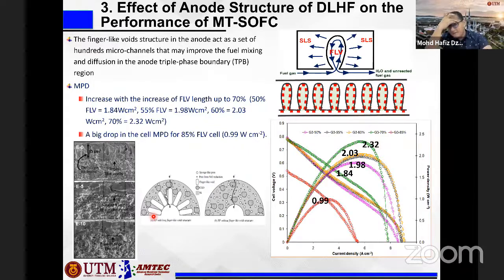But if you have the finger-like structure, we expect that it can create a vortex flow, meaning the fuel will go inside the finger-like structure and disperse throughout its boundary, so the fuel can reach more area in the anode. By having this mechanism, we expect that all the area deep inside the anode can also provide some reaction, and therefore it can produce more electrons. So we can have higher power density. This is what we predict, we hypothesize, from the structure.